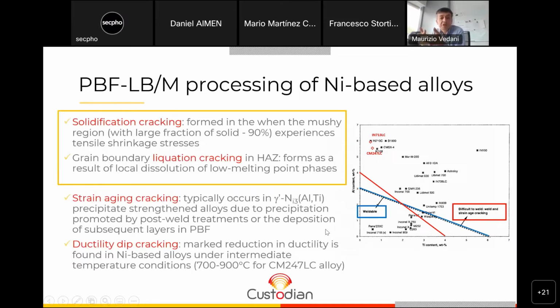What are the challenges when processing such alloys by PBF with a laser beam? There are a number of issues, a number of defects that can be generated within the material. The most important are the first ones listed here in this list of 4 concerns. We are talking about solidification cracking, in terms of cracks that are formed in the very last stage of solidification when we have a fraction of solids already of around 90% due to the tensile shrinkage stresses.